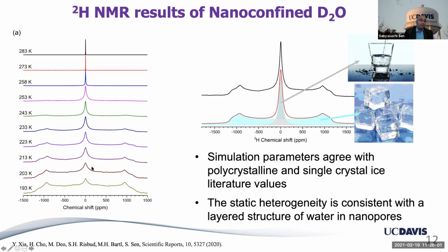Eventually, with increasing temperature, the liquid-like component increases in its fraction as it should, but well below the nominal melting point, which is, let's say, around here, well below that, you can see the presence of this liquid-like component. And this stays forever. It's not like this is a function of rapid cooling. At each of these temperatures, we can hold it for, say, up to an hour. We tried and nothing happens to the line shape.